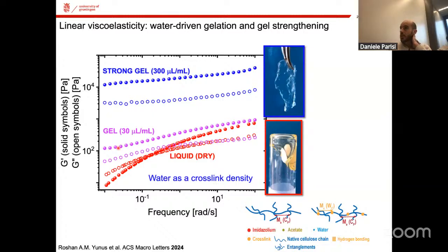So something that we noticed is the fact that there are two plateaus in G prime. One is here in the high frequency, and one is here in the low frequency. This one, which is very close to the dry state, is the elastic modulus related to the entanglements. Or you can imagine the network of polymer chains like this, where the entanglements in physics are physical constraints between chains from the theory of de Gennes and Edwards.